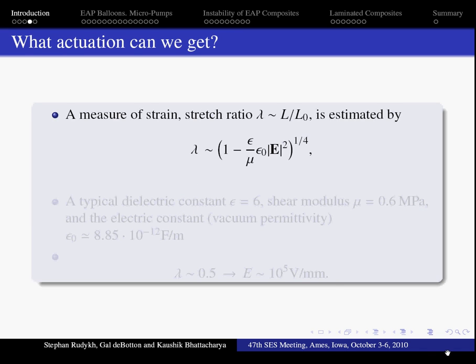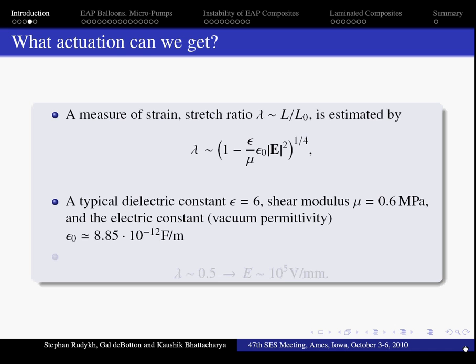So what is the voltage that we need to activate such device? Here is the relation between stretch, lambda, and electric field, E. And let's take typical values of the electric constant and shear modulus. And we see that to get 50% of deformation, we need this huge amount of electric field.